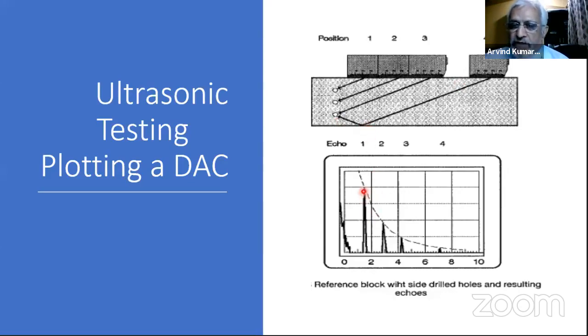So for the first one, I have to adjust the probe such that I get a peak. Where I get a peak, I mark that point as point number 1, and then go to the next place. Again, when I pick up this indication, I try to maximize it, and I mark this point as 2, where I get the maximum indication. Then I go to 3 and mark the maximum as 3, and then 4, which is shown very low here. Then I join these peaks, and this dotted line is my DAC, the distance amplitude correction curve.